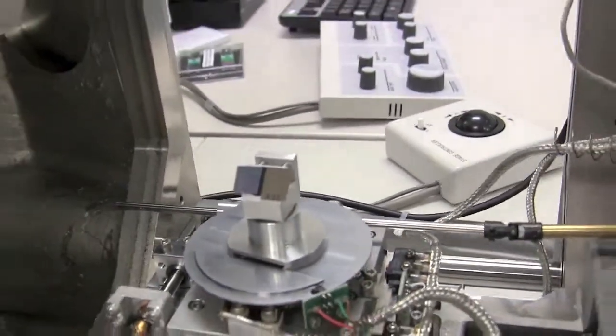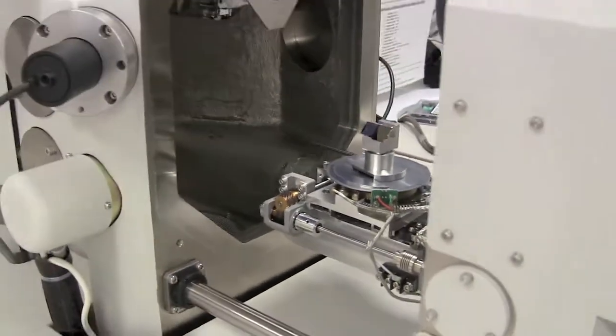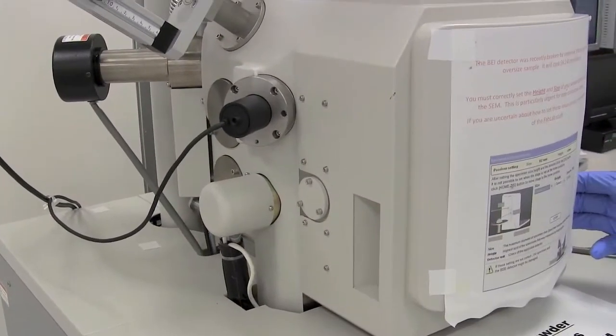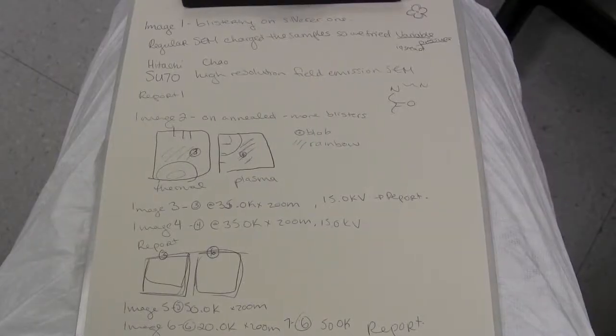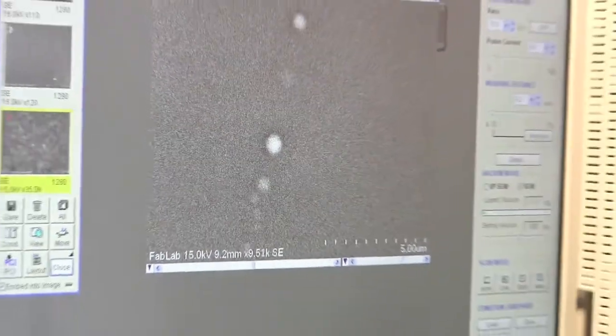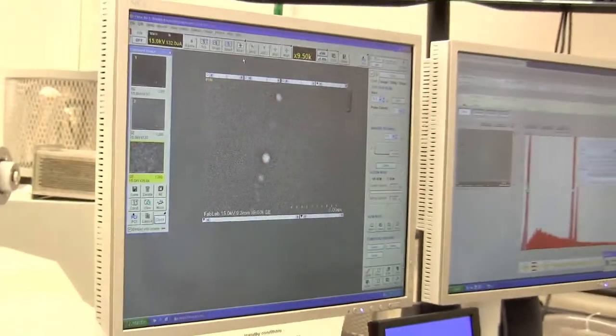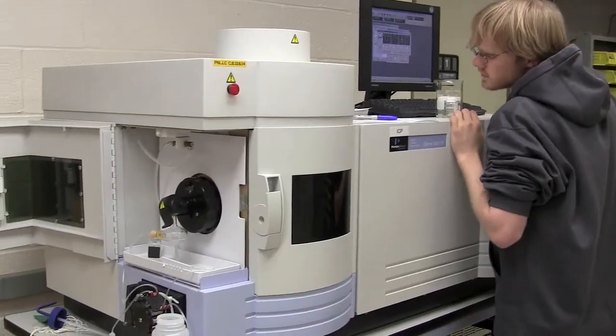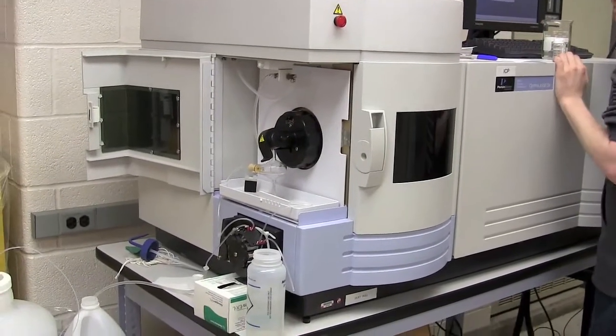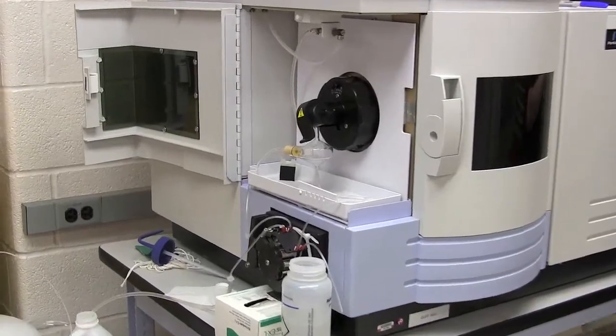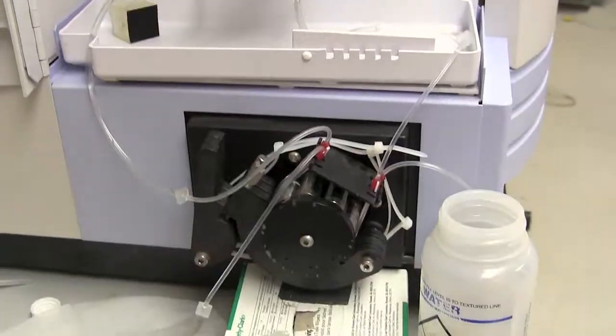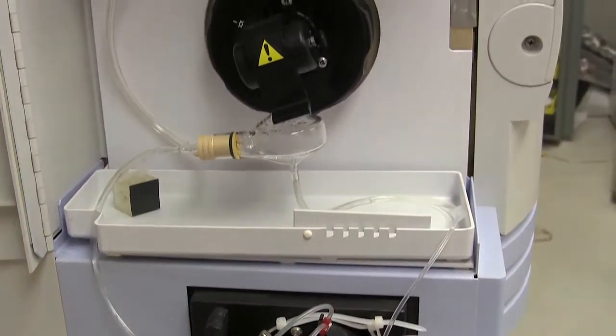EDS analysis showed that after incubation, there was more chlorine on the dendrimer-coated samples. We believe this is because the chlorine ions get caught in the dendrimer branches and remain even after washing. In addition, ICP-OES revealed that dendrimer-coated samples released fewer titanium ions in the surrounding solution than our control, which supports our theory that the dendrimer coating is preventing chlorine from reaching the oxide surface. These results uphold our initial hypothesis that a dendrimer coating would decrease titanium corrosion.